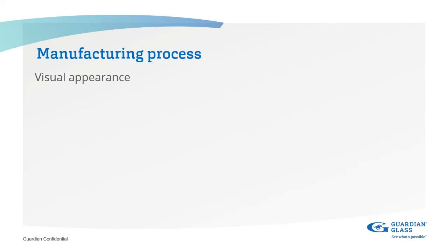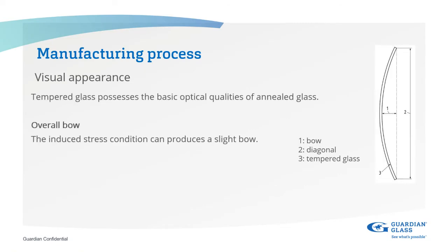Manufacturing process, visual appearance. Okay, so again, tempered glass, overall bow. If during the tempering process you have a cold side of the glass when it enters the furnace, the glass can bend inside the furnace. So if you have a different temperature from the bottom of the glass to the top of the glass, when the glass exits the furnace and enters the quench section, then this can cause what we call overall bow. Now this can be controlled inside the furnace, and it also can be controlled in the quench section as well.